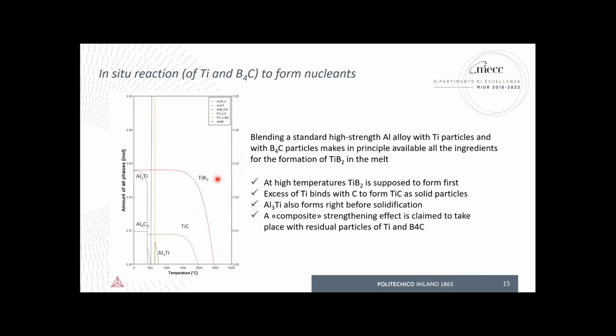So from the melt, first we have the generation of TiB2. Then, as we mentioned before, we also have the generation of titanium carbide, then Al3Ti. Then here, the two lines, the yellow and the blue line, I forgot to put labels here, sorry. They correspond to solidification. Actually, the blue line should be the liquid that is going down to zero at the solidus temperature, and the yellow line is the solid alpha phase that starts growing from the liquidus temperature, and then will go very high, up to 90 and something percent.